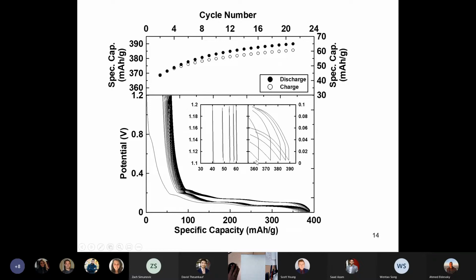And in this little panel, they show you how the endpoint changes every 5 cycles, not every cycle. This is cycle 1, cycle 6, and so on. And then you also do the same thing for the charge endpoint. And again, you can see how the charge endpoint moves along as the cycling increases from cycle 1 to cycle 6 to 11 and so on. Okay, and these two curves are roughly parallel, and that's because the cell capacity isn't changing. The endpoints are both shifting by the same amount in the same time, roughly.